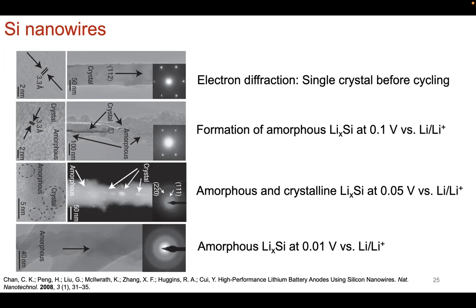So that goes to show you that at the nanoscale, the fact that silicon nanowires are undergoing this amorphous transition is stabilizing the kinetically induced lithium-15 Si4 phase that you would normally get under thermodynamic equilibrium in the bulk phase. And thus you never actually get to Li22Si5.